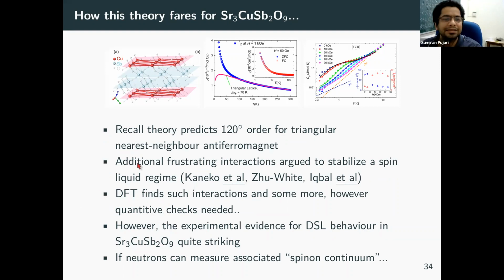One final comment is that theory actually predicts 120-degree order for the triangular nearest-neighbor antiferromagnet, as I mentioned before. So to even potentially stabilize a spin liquid, additional frustrating interactions have been argued to be needed, and DFT indeed finds such interactions. Of course, we can't estimate them from experiments because they are much smaller, 1/10th or even smaller than that. So some theoretical quantitative checks are needed to see whether, in the presence of the interactions that DFT finds, you get a spin liquid or not.